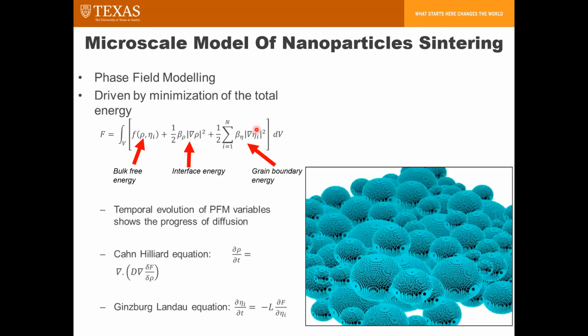So now I'm going to go into a bit of detail on the modeling efforts. The modeling of the solid state nanoparticle sintering is done using a phase-field modeling approach, where the sintering is driven by the minimization of the total energy in the system. And this total energy is a function of the bulk free energy, the interface energy, and the grain boundary energy.